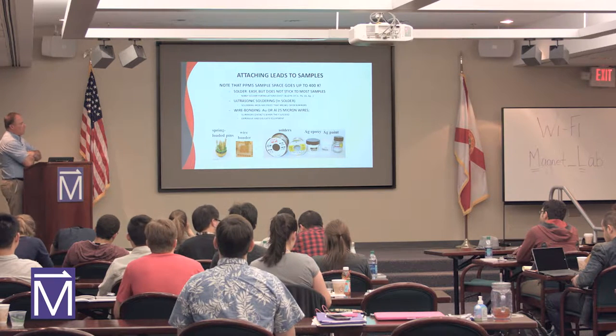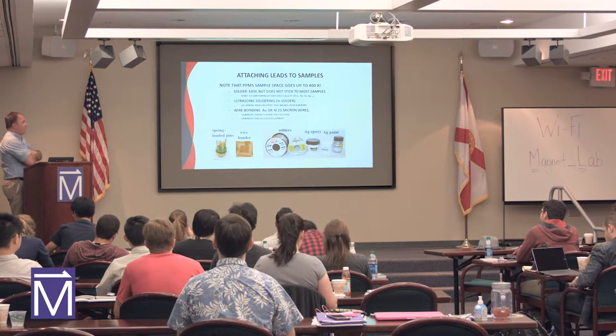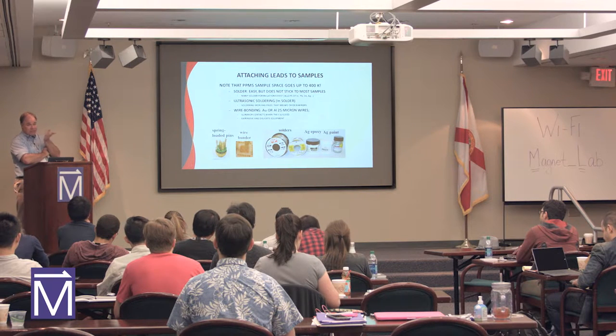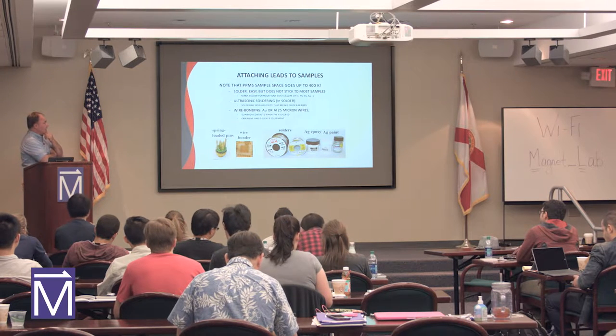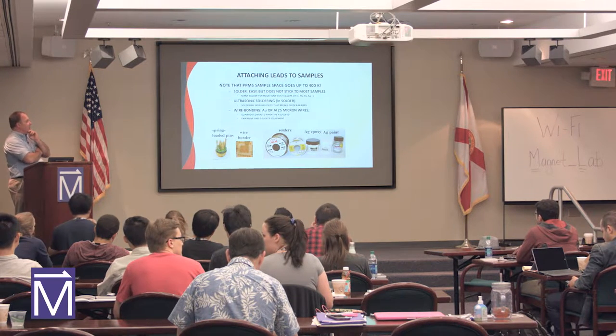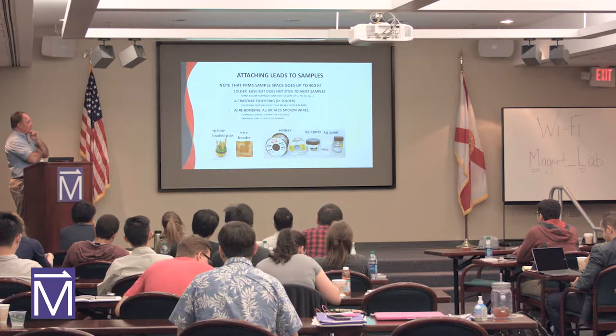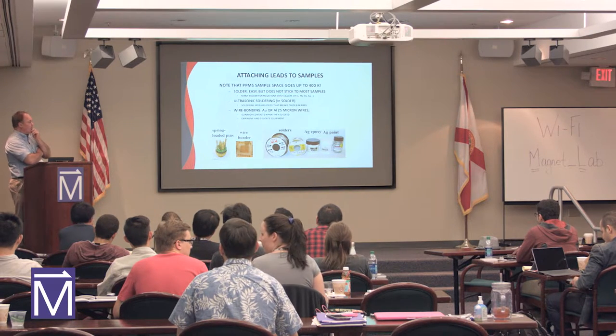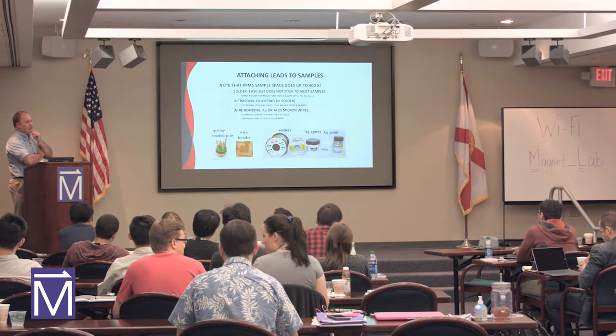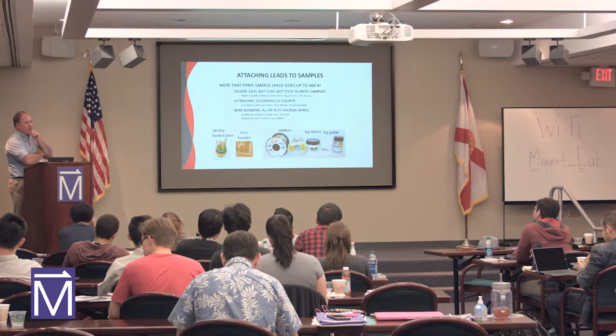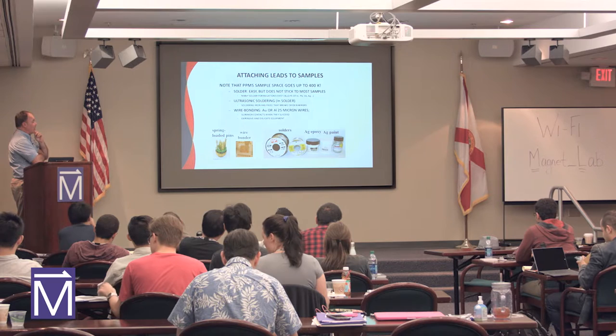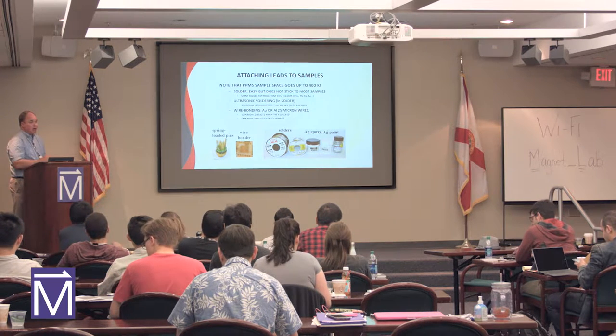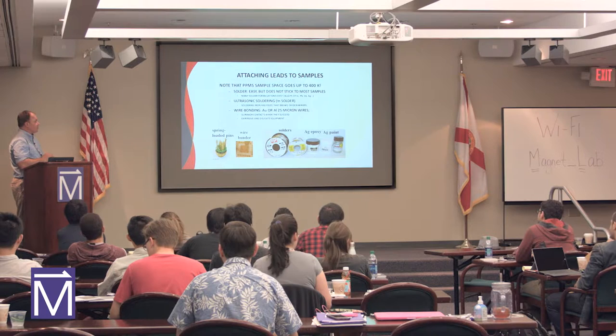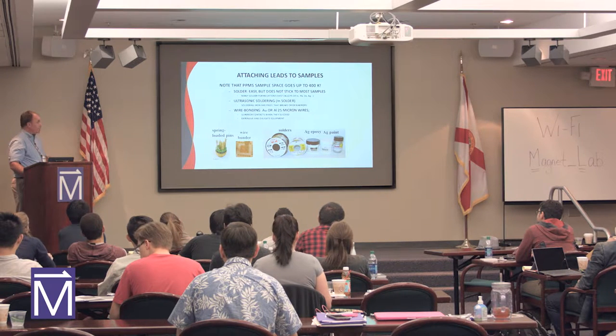So you can use solder to attach a sample. The solder has many formulations. We do a little experiment in the BSM to show you the magnetism of the solder. The solder may not stick, though. Indium soldering, so you can use the ultrasonic soldering with the indium to break down the oxide layer that's on the solder. Wire bonding, so if you have access to a wire bonder, you can put a wire bond connection. That's probably what a lot of people do, to put the fine wires to make your sample connections.